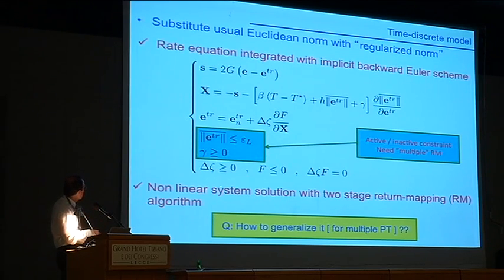However, for such a model, we were able to devise what I name a two-stage return mapping algorithm, in order to, we have, let's say, 2 trial states in order to see which constraint is really active. So for this model, we can stay within the return mapping algorithm, and you can extend the classical plasticity return map algorithm in order to devise a sufficiently robust numerical scheme. But in any case, let me stress that this model is not too easy to treat numerically, and you can come up with some problems.